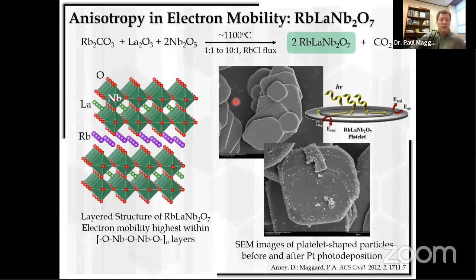Let me move through this a little bit more quickly now. Here's another example where you have a layer type structure, the Dion-Jacobson phase, rubidium lanthanum niobate, and it's constructed of NbO6 octahedra that condense together into a 2D layer with rubidium separating those layers. And as I described earlier, electron mobility is going to be the highest within those layers.